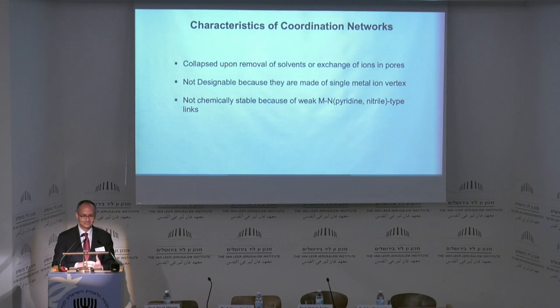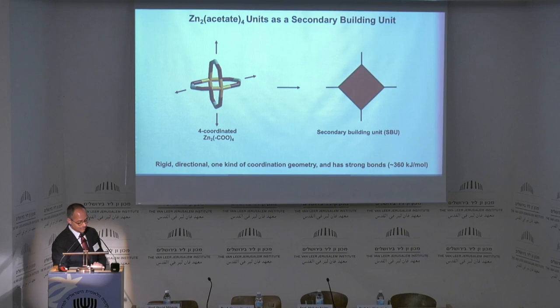A serious experiment was, as an inorganic chemist, I realized that you need to move away from neutral linkers and start with charged linkers. A charged linker, when linked with a metal ion, you have, in addition to the covalency of the bond, the ionic interaction, and that made it much, much stronger. In fact, twice or three times as strong as a neutral linker. And that was the first thing, to create a stronger bond.